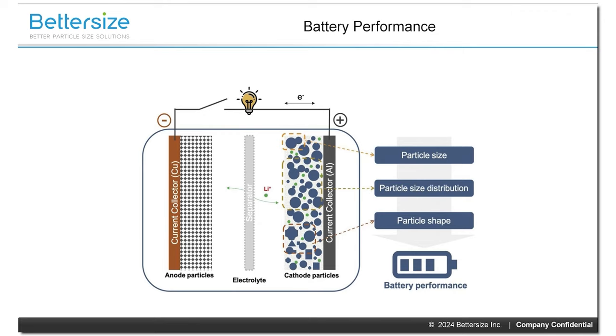The key to efficient lithium-ion batteries lies in the effective contact between the lithium-ion-rich electrolyte and the active material particles in the electrode. The particle properties of the electrode materials affect the diffusion path, diffusion resistance, the contact area with the active material, the electrochemical performance, and the energy density of batteries. To achieve good performance of lithium-ion batteries, it is not only necessary to focus on the modification of materials, but also to balance the properties of electrode material particles. And these properties that we should consider are size, size distribution, and shape.